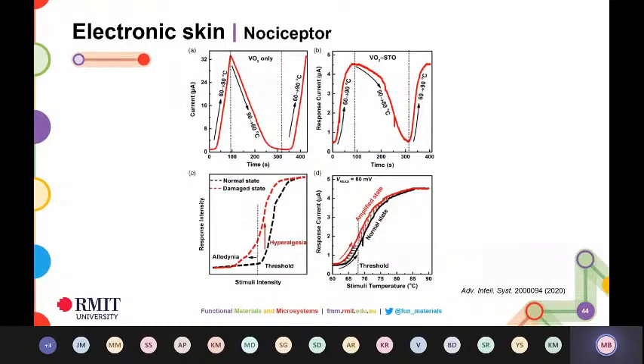The fascinating last concept in the electronic skin was the demonstration of the nociceptor concept. This is where you're trying to demonstrate that our skin doesn't react to every single stimulus. It only reacts to stimuli once it exceeds a particular threshold. But there are people who have a lot of skin conditions which make them extra sensitive or hypersensitive to external stimuli. These are allodynia and hyperalgesia. Allodynia is where even below the stimuli which you normally respond to, a person starts reacting very, very strongly to the stimuli. For instance, say your skin is sunburnt, then you react very differently to the presence of stimuli. Hyperalgesia is where you have a very strong response. So even a tiny amount of pain, which most people are able to endure, is unbearable for people who have hyperalgesia. Using vanadium dioxide with the strontium titanate allows us to demonstrate these damage states in our skin as well, because you're able to control the threshold at which the skin starts reacting to particular stimuli.